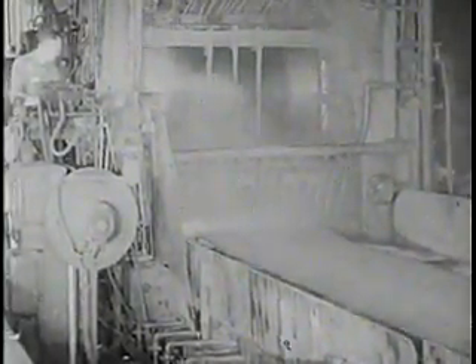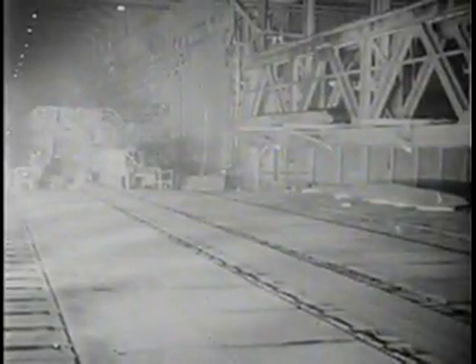Monster machines, marvels of mechanical ingenuity. The total weight of each is well over 1,000,000 pounds. Emerging from the last finishing stand at a speed of about 1,250 feet per minute, the hot rolling process is completed. One of the slabs from our 23,000-pound block of steel has become a strip 600 feet long and approximately 1/16 of an inch thick.